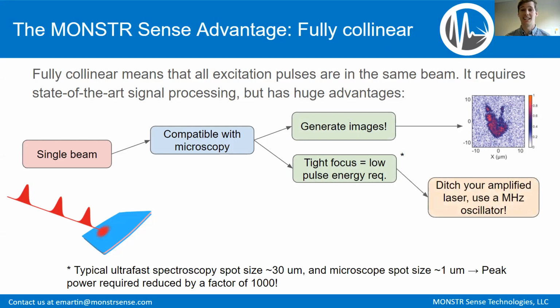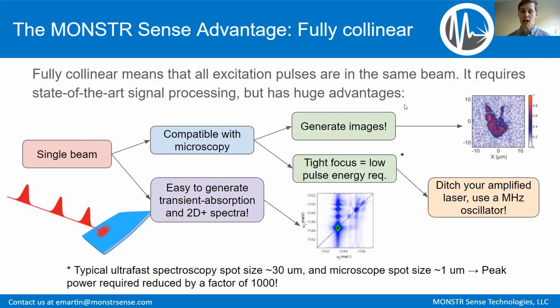What this means for you is that you can ditch your amplified laser and instead use a megahertz oscillator. Megahertz oscillators now with OPO technology are great at spanning the full wavelength range that you want to access from UV through IR. And so this is definitely a great alternative to the conventional ultrafast spectrometers using amplified lasers. Another thing that's great about having a single beam is that it's just easy to use. The non-collinear geometries get a lot more unwieldy, particularly as the techniques get more complicated with more than 2 pulses. And so with our software and the geometries, it's easy to keep the system aligned. It basically remains aligned, and so it's easy to generate transient absorption and 2D spectra.